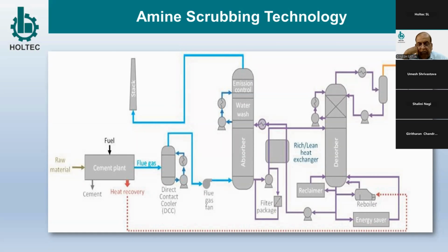It will be pumped and preheated and sent to the stripper, also called the desorber column. There it will be heated to 120 to 130 degrees, and it will release the CO2, and lean MEA is recovered and pushed back into the system. The CO2 separated from there is compressed. That will have 95 to 99% purity, and it will be pumped through a pipeline or to storage or a tanker or whatever means for further use. So this is a simple process. The process is not simple, but I have explained it in a very simplistic way.